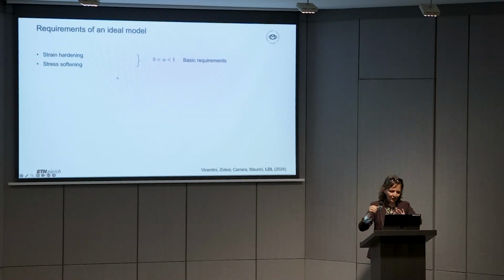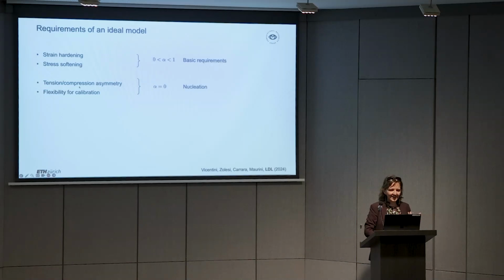So, before I move forward to the second part of my talk, what are the requirements of an ideal model? I'd like to nail them down now. So, we said we want strain hardening and stress softening in the intermediate range of damage, so between 0 and 1, but we also want ideally to be able to control the tensile strength and the compressive strength, ideally the shape of the strength surface, the shear strength. So we really want to be flexible to calibrate the strength surface, which is not possible, as we have seen with the basic model. And these are requisites that are related to the critical value of damage, which for alpha equal 0 is the nucleation requirement.